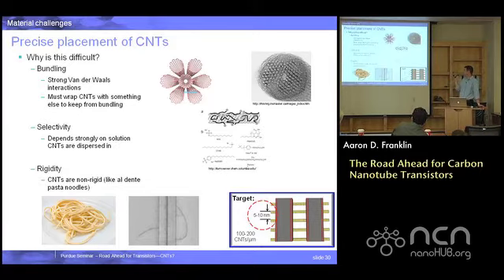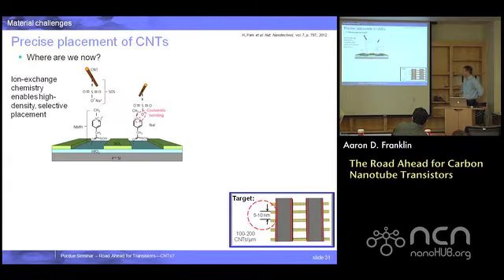There's an interaction, the van der Waals force, that lets the nanotubes join together, depending on what solution they're dispersed in, unless you put something on them to specifically keep them from doing that. So those are the two biggest issues with respect to controlling the material when you want to position it on a substrate. So I'll highlight one of our approaches. There's actually a few good papers that have come out in the last year or so that have unique approaches for solving this problem, or at least on the path towards solving it.